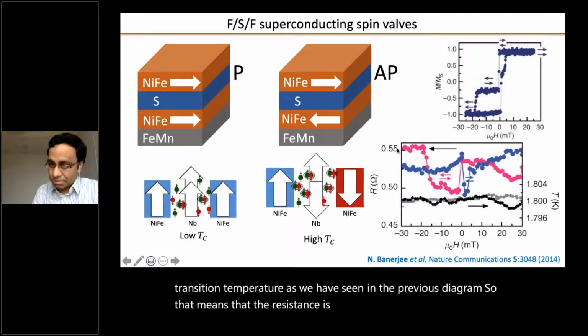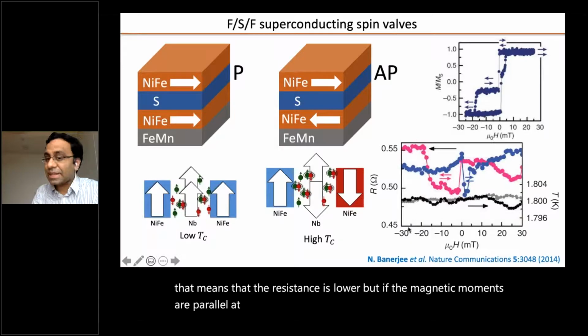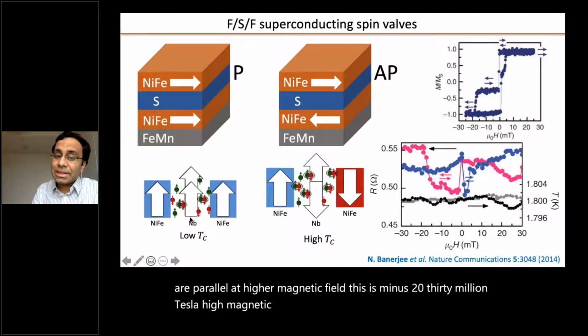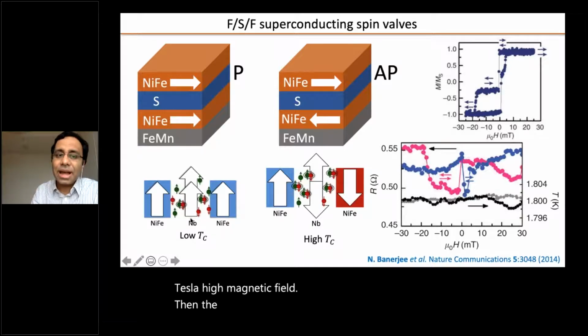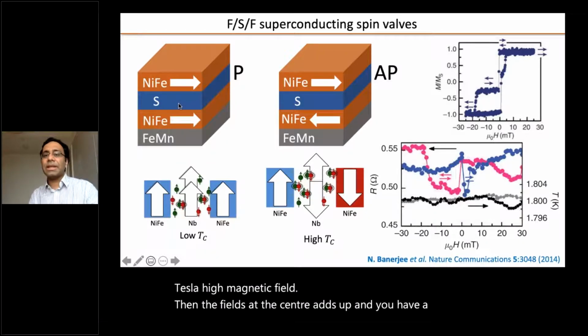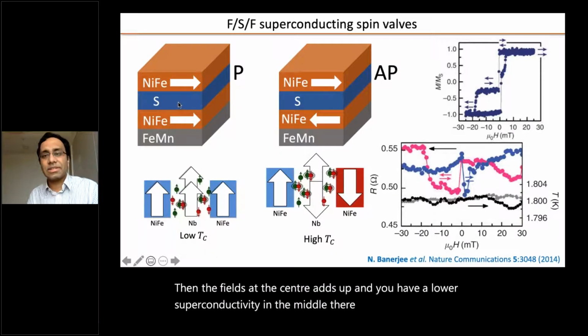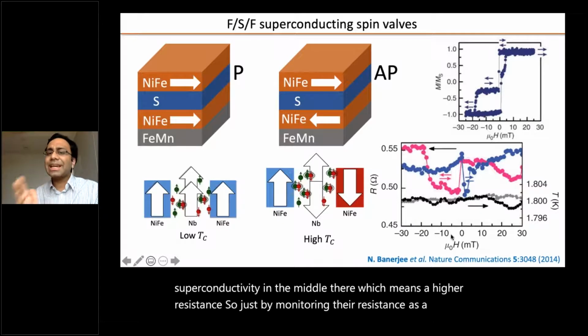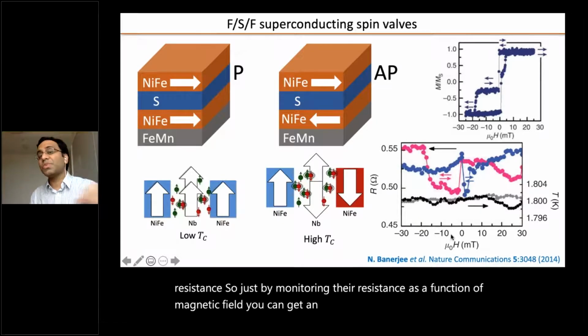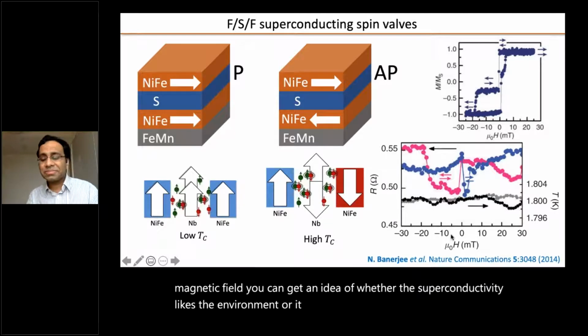But if the magnetic moments are parallel at higher magnetic field, this is minus 20-30 millitesla, then the fields at the center add up and you have lower superconductivity in the middle layer, which means a higher resistance. So just by monitoring the resistance as a function of magnetic field, you can get an idea of whether the superconductivity likes the environment or it doesn't like the environment.